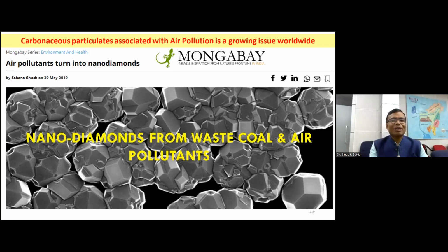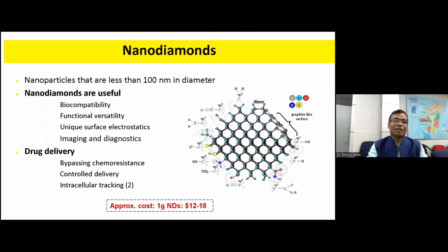And this air pollutant is nothing but carbonaceous products, and basically it also consists of black carbon. So our curiosity was to see whether this black carbon can be collected or deposited, and then converted to value-added products. And in a very exciting experiment, we found that these air pollutants or carbonaceous particulate matters have been converted to nanodiamonds, which is a very futuristic material and also a very high cost material, which has also been featured in one of the international magazines, which I showed in the earlier slide. So you can see the nanodiamond structure.